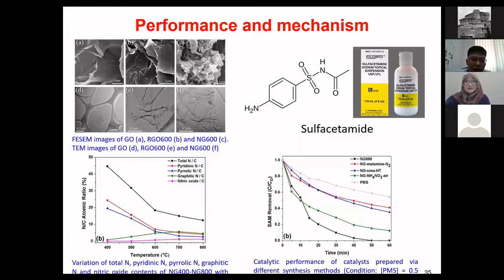So if you look at nitrogen doping, if you use 400 degrees Celsius for your synthesis, you can see a lot of this nitrogen will exist in this one, red color, pyridinic N. So if you increase the temperature, then somehow you increase the graphitic nitrogen. Okay? So the graphitic nitrogen is the one that we want for our application, because graphitic nitrogen is the one that will lead to non-radical reaction, which is a pathway that we want for PMS activation.